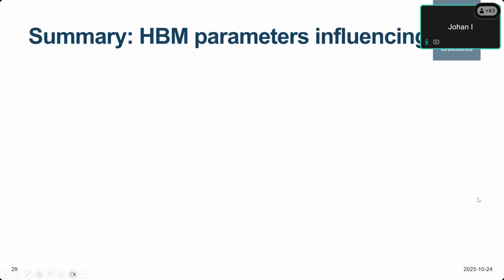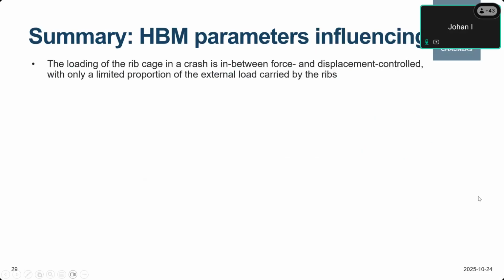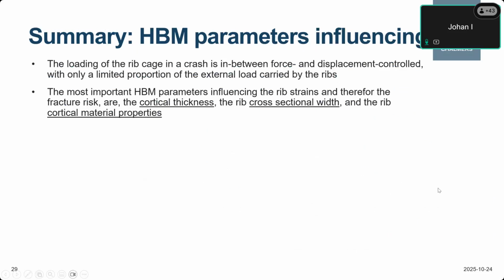So, a summary of the parameters influencing the strain. The loading of the rib cage in a crash is somewhere in between a force and displacement control system, with only a limited portion of the external load carried by the ribs. The most important HBM parameters influencing the rib strains, and therefore the fracture risk, are the cortical thickness, the rib cross-section width, the smaller of the two dimensions of the rib, and the rib cortical material properties.